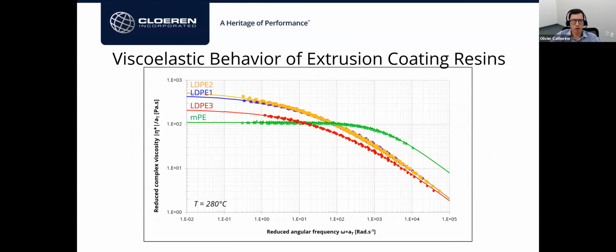So now if I compare the complex viscosities, you can see that for my reference material in blue here, we did see a little bit more melt elasticity for LDPE2, and you can see that that translates into a potentially slightly higher zero shear viscosity. But at high frequency, we have a very good match in shear thinning.